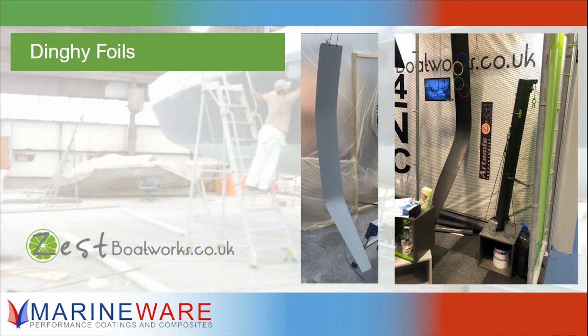Durepox Clear was originally used on the foils of the America's Cup foiling boats, but when they moved up to the AC75s, the really big ones out in America, when they were racing under the Golden Gate Bridge, they struggled a little bit because the hydrostatic loads just going through the water were so big. If there were any adhesion issues in the paint, it would exploit them very quickly. And they actually invented Durepox Extreme for that.